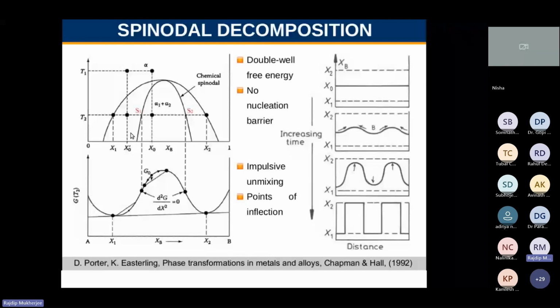So if you go to a composition, say x dash 0, from T1 temperature and you quench it into a T2 temperature, the phase separation will take place by nucleation and growth mechanism, which is a precipitation mechanism. Because if there is a small fluctuation, it will not grow because the free energy is going to increase. But if there is a large fluctuation, it's a nucleation, then a phase separation will occur, right? So typical free energy curves are double well free energy curves in case of spinodal decomposition or precipitation for this kind of phase separating process.